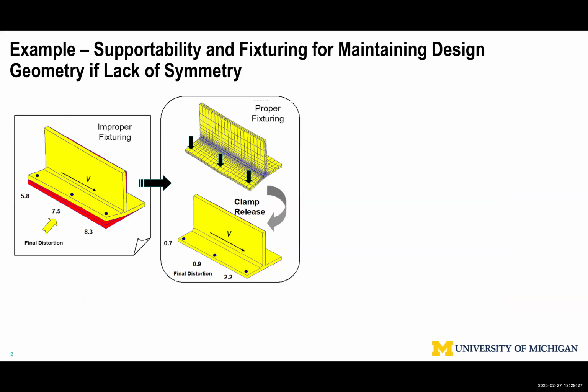Sometimes we don't have symmetry because by definition, ship structure is very complex. Here I'm using an example to illustrate when you weld a T-stiffener, looking at the titanium. Because the titanium extrusion is very expensive, we had to use a fabricated T-stiffener. You tie them together, you put this weld together, and you measure from the flat surface 5.8 millimeter, 7.5, 8.3, that's already out of whack. Imagine you're going to do 20 feet.